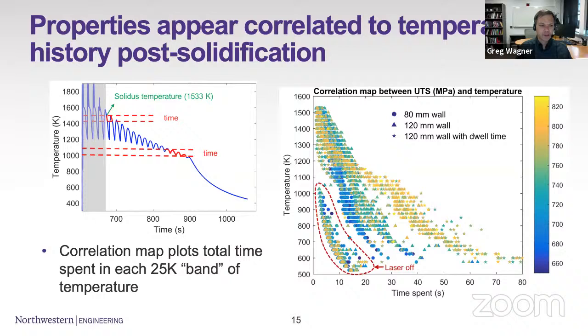So what if we start to look at the rest of the cooling curve, so beyond just the solidification region? Here's a sort of simple way of looking at these correlations, and in the end, maybe not our final way, but it's a way that we can see some information. So we took each one of these temperature histories, and binned the amount of time that was spent in each individual 25K band of temperature, right? So basically, look at the region between 1000 and 1025 degrees K, count up in total how much time was spent in that band, and then plot that against the ultimate tensile strength or any of the other properties that we measure.